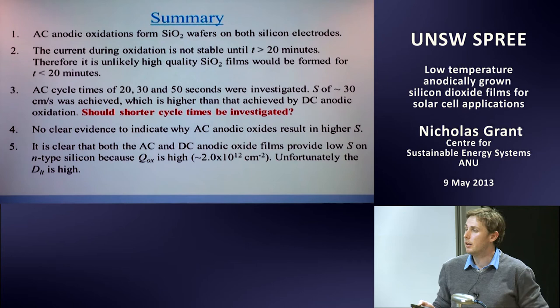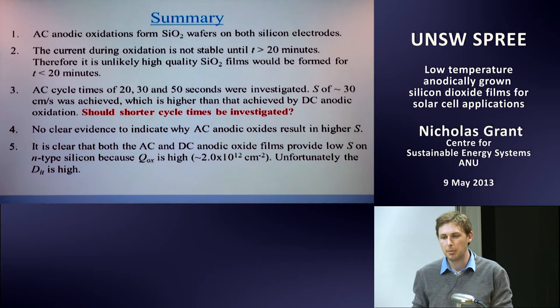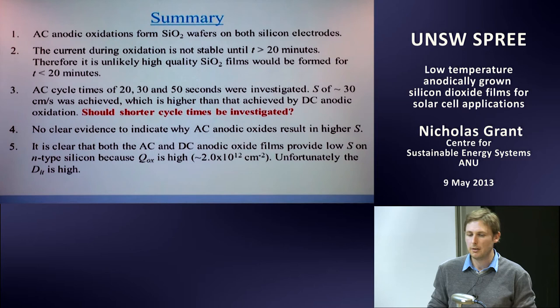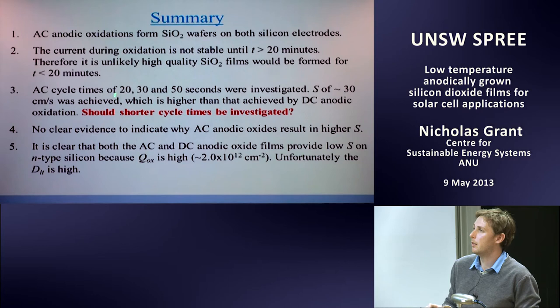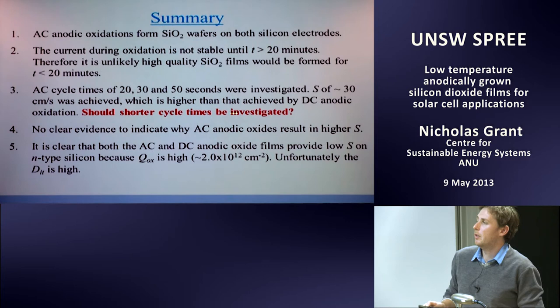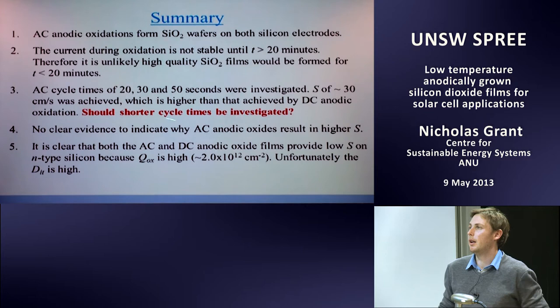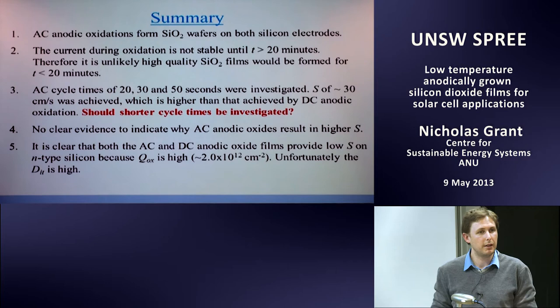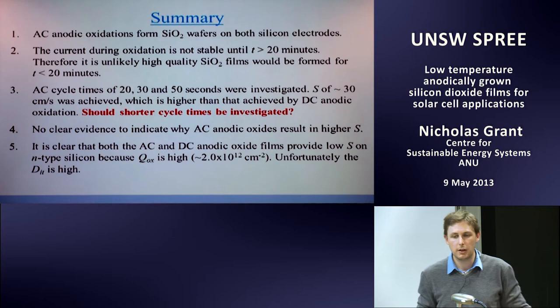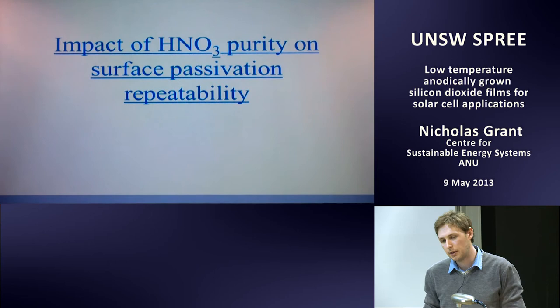Summary of the AC section: AC oxidations can be performed on both wafers simultaneously. The current during oxidation is unstable for times less than 20 minutes but stabilizes after that, so passivation for times under 20 minutes will likely be poor. We examined cycle times of 20, 30, and 50 seconds with no real trend — shorter cycle times may need to be investigated. There's no clear reason why AC oxides achieve higher surface recombination than DC oxides. All films have a high charge of around 2×10¹², which is good for n-type.